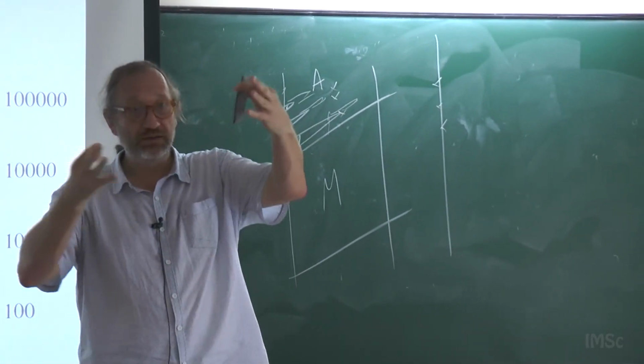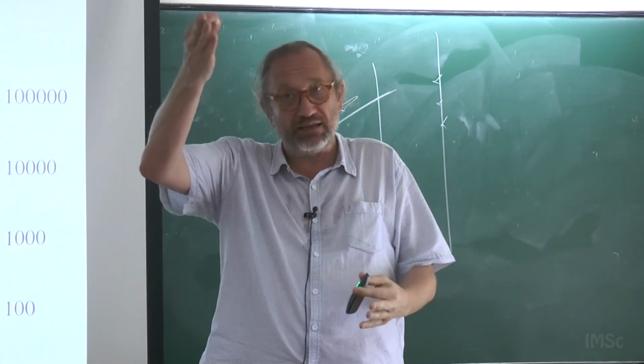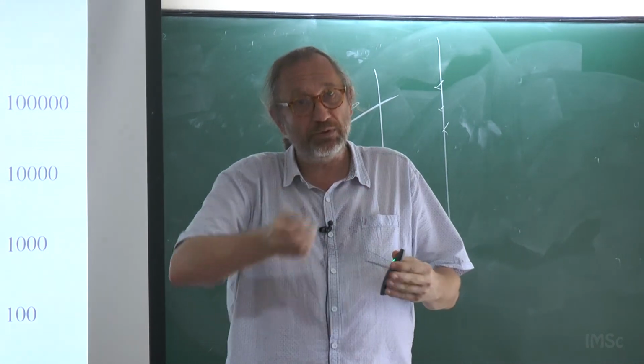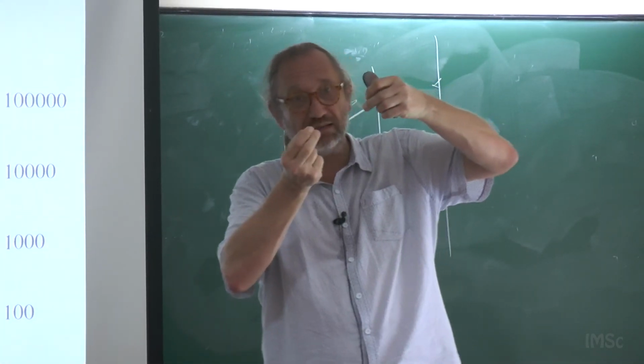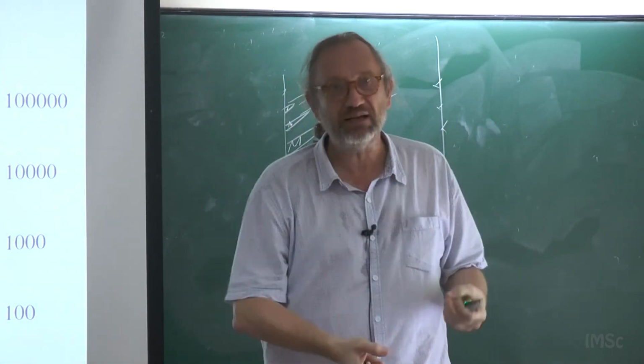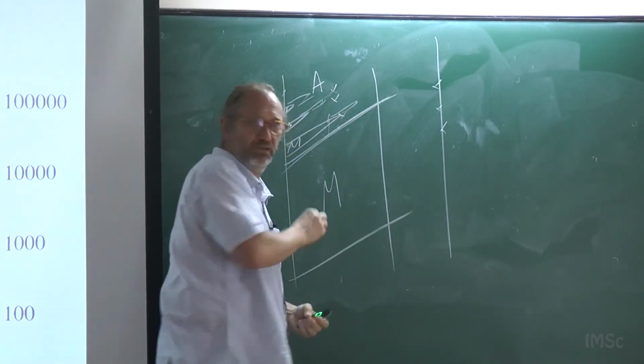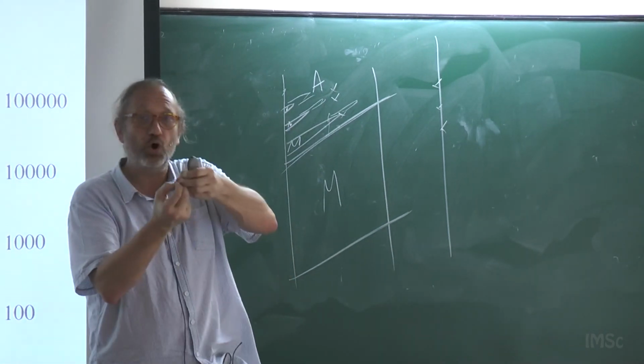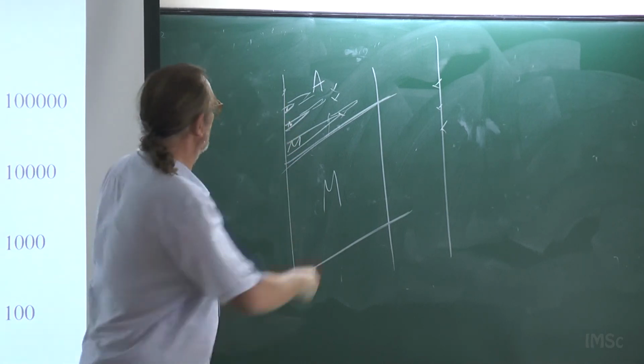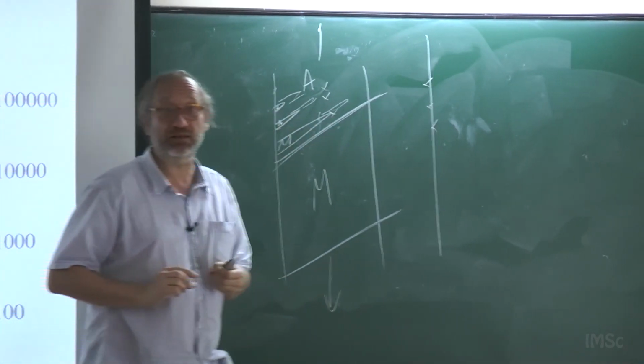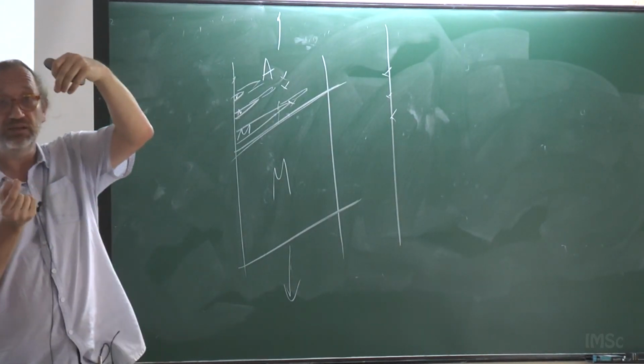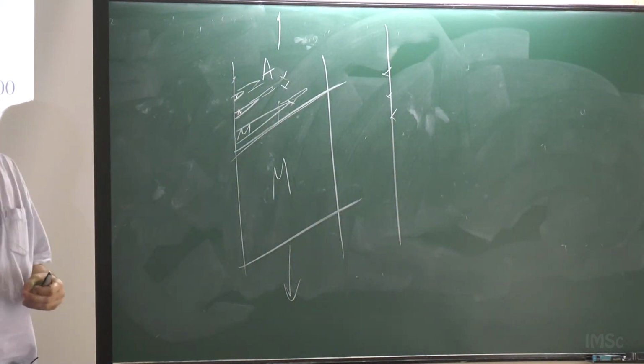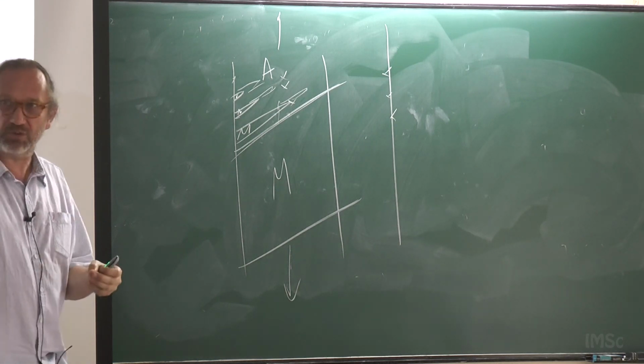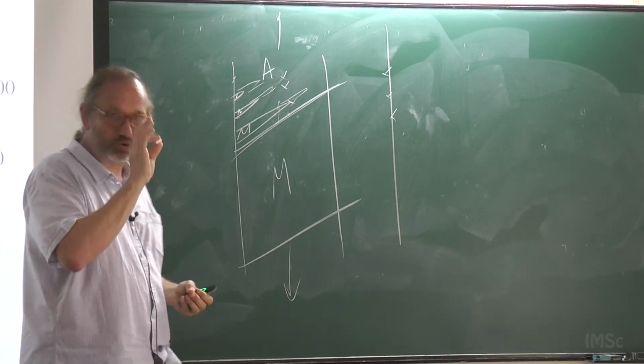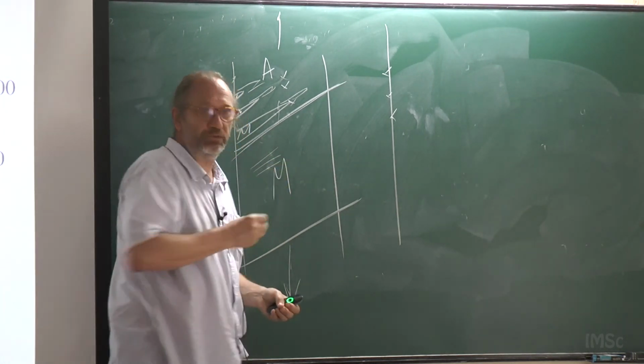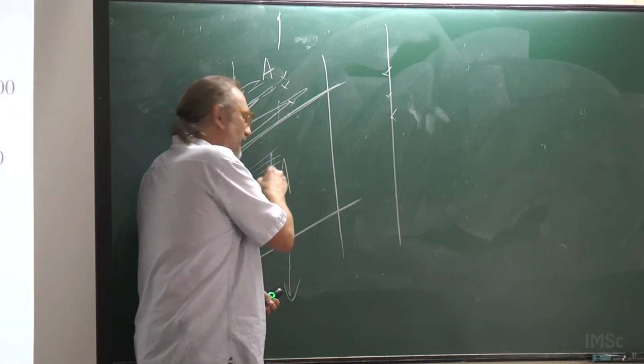And it's known that, given the symmetry of the austenite and the martensite, the interfaces can only occur, because there is no diffusion here, so the atoms are always in the lattice, in certain lines with a certain angle. This angle can be perfectly calculated. Because in this case, we are growing only one variant, the one that is favored by the stress that we are applying. Given the orientation of the monocrystal, there is only one variant that grows. Well, if there's somebody that works with martensitic transformation, it could be one variant or two, because sometimes this martensite is what they call twinned martensite. So maybe this is two variants, but this is another question.